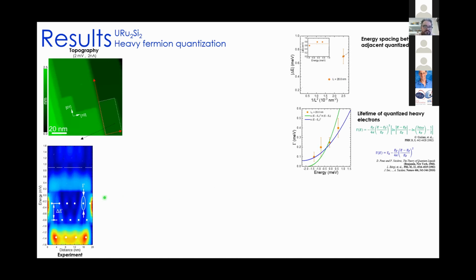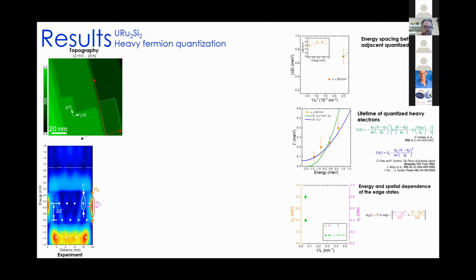And finally, we also analyze the step states. We use this expression to fit our data at the edge state, measuring the energy and the spatial dependence of this state with this sigma sub E and sigma sub X that we mark here. And also I plot here just the values that correspond to this terrace.